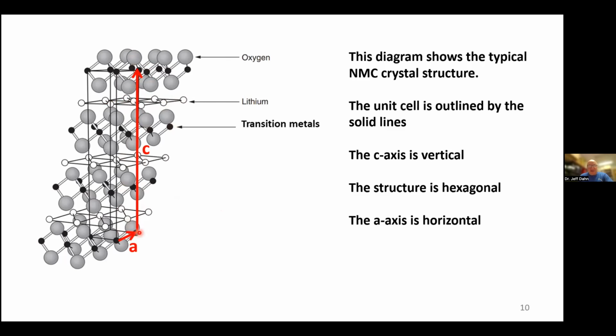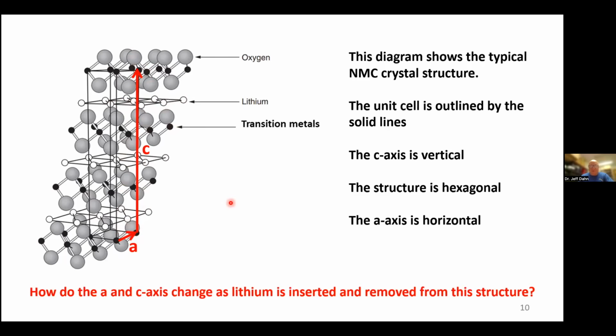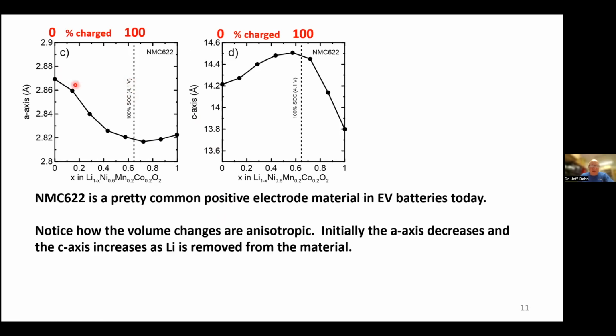So how do these things change as the lithium content changes? So here I show a graph that shows how this A-axis and how this C-axis changes with the lithium content in NMC 622. And I put on the top axis where you would be if you were 0% or fully discharged, and in a typical EV where you would be at 100% charge. And you can see that there's a significant variation in both of these parameters. But what is most concerning is one of them shrinks and one of them expands during this change in the lithium content or change in the state of charge of the material. So the volume changes are anisotropic.